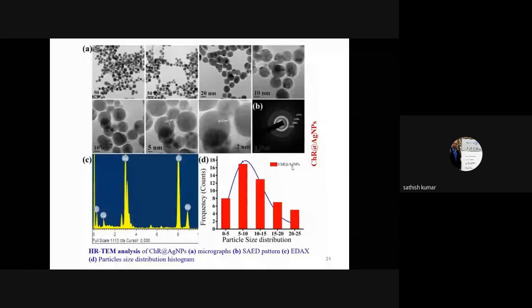And this is the EDAX analysis. This is a preliminary screening of the elemental composition. Earlier we saw the XPS analysis, where you can find the exact elemental composition, but this EDAX is a preliminary screening of the elemental composition. Here we found the maximum signal for silver, and the carbon and oxygen are due to the presence of chrysin, and the copper is due to the grid that we have used for the TEM analysis.